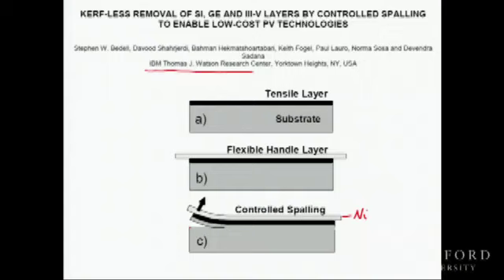And when you yank it off, it cracks, and a crack starts. But the part of the silicon that's very close to the nickel is protected by the compression of the nickel, because something under compression doesn't crack. And you end up, in a controlled way, peeling off a film approximately 20 to 50 microns thick, which is exactly the right thickness for a silicon solar cell. So this is really pretty amazing. And of course, this completely knocks the cost out of silicon. Whatever the Chinese subsidy is now is kind of irrelevant, because this will greatly reduce the cost of the silicon.